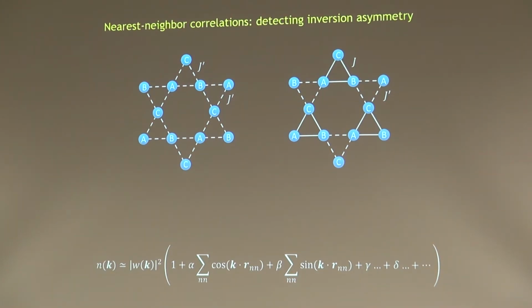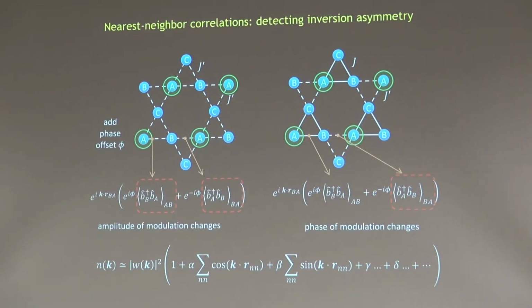So how do we distinguish the signature from one of these bonds from the other one of those bonds? The way we do so is by applying phase shifts. So now we're going to take these coherence functions, which are strictly real in the ground state, and we're going to make them complex functions. We're going to do so by changing the energy of one of the sites within the triangular plaquette, which we can do just by switching off one of the lattice beams transiently.